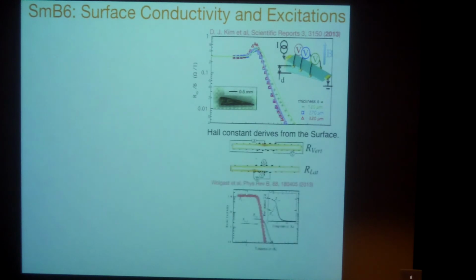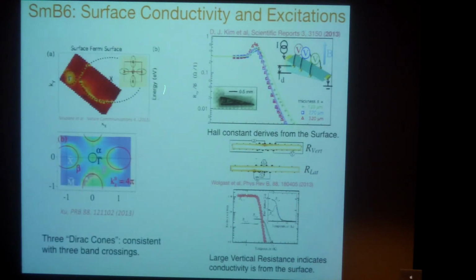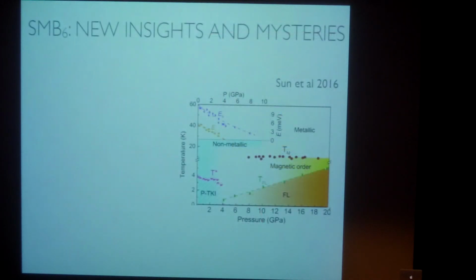We know this system has surface conductivity. The Hall constant derives from the surface. If you do non-local conductivity measurements, you can see that conductivity runs around the edges. And if you do ARPES measurements, you can see some large Fermi surfaces on the surface, 3 Dirac cones consistent with 3 band crossings. Everything looks fine. However, there are a lot of anomalies we don't understand.